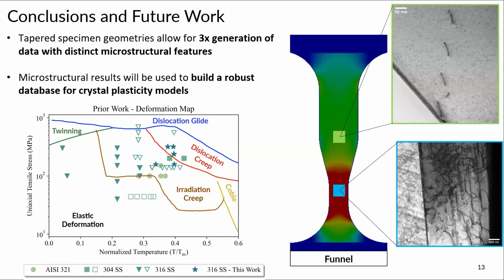Yeah, so you put it into the TEM, that's the transmission electron microscope. So we basically take these things called lift outs. You use focused ion beams to mill it out of your bulk material. So the specimen that I've irradiated, then you thin it down.